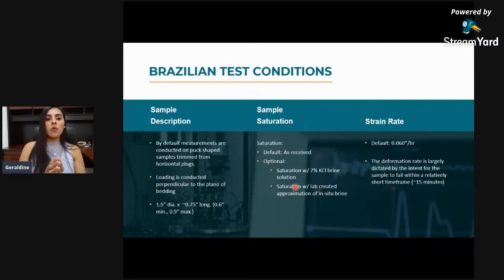For this test, we suggest to do this in 1.5-inch diameter samples. Why? The bigger your sample, the less influence of any heterogeneity you will have in your results. It means if you have any heterogeneity, like a little fracture or sample grain, it will affect less if you have more area of sample. Sample saturation is the same as compressive strength. Normally they are run as received with no saturation, but if you decide to do this with saturation, the standard is KCl at 7% or any brine created in the laboratory.